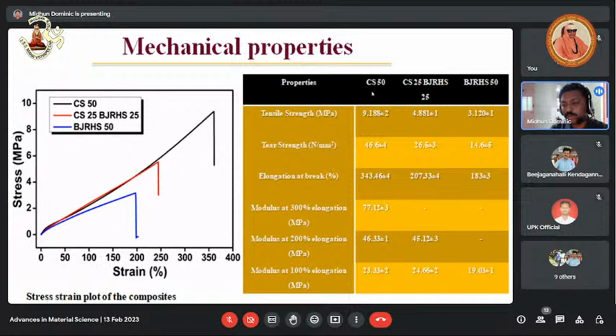It is for commercial silica 50. If you make use of 50 grams of commercial silica, the tensile strength is 9 megapascal, but it is significantly decreased to 3 megapascal if we make use of BJRHS. So we were disappointed with the results. But what might be the reason for that? Even though BJRHS has excellent surface area, high purity, and low particle size, the properties are decreasing.